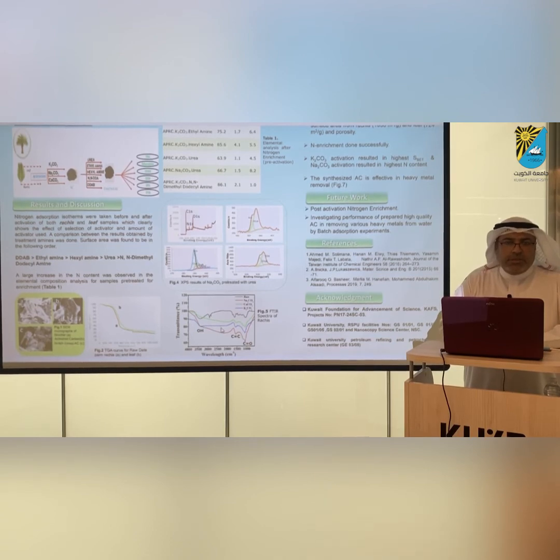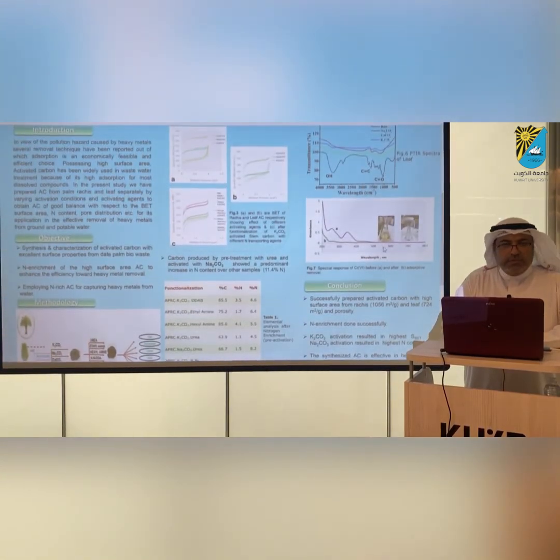Of course, after that we have to test the functional groups. To study the functional groups, the best technique in chemistry is the FTIR. It will tell us whether we have carbon-carbon double bonds, carbonyl groups, hydroxyl groups, and other nitrogen-containing groups. So we did the FTIR for both parts of the palm, and then we tested for the removal of the heavy metals. You can see here we succeeded in removing almost 98% of the heavy metals, but of course we have to control the pH. We found the pH is very important. The lower the pH, the better the efficiency of the activated carbon. We found pH 4 is excellent for removal of the chromium(VI) ion.